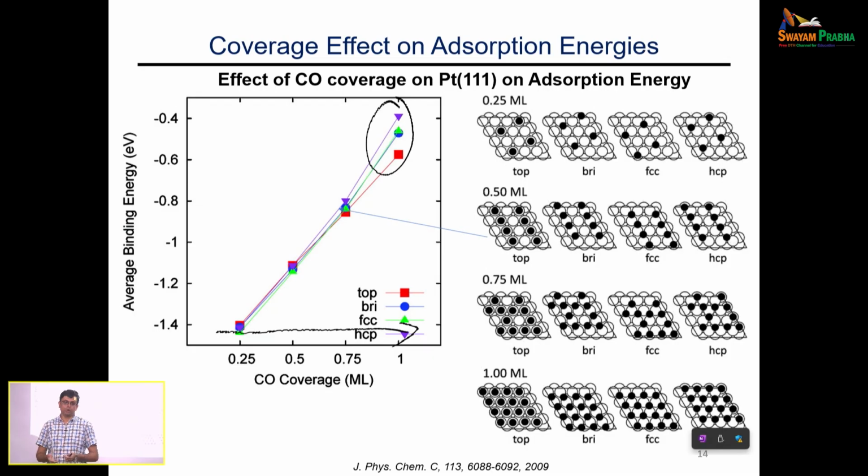So when you have adsorption in practical scenarios, that is something that you need to think about, and that's where the isosteric heat of adsorption becomes useful, because it tells you what is the heat of adsorption at specific coverages that you have, okay? And that's precisely something that we can estimate this way as well. So again, apart from talking about points of contact and so on, there is a coverage impact.